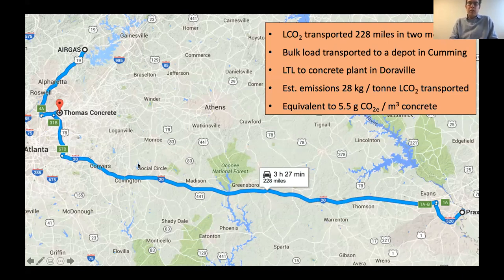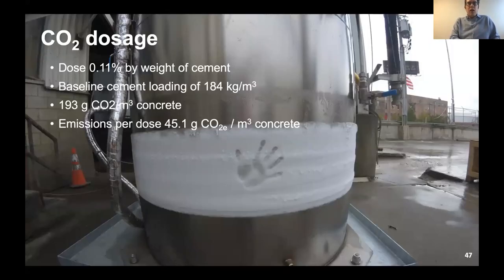And so we can look at the transport emissions for those two transportation modes, and we come up with about 28 kilograms of CO2 emitted per ton of liquid CO2 transported. And if you look at that on the unit basis, we're down to 5.5 grams of CO2 per meter cubed of concrete. If we talk about dosages, this producer is using about 0.11% by weight of cement dose for their mix designs,